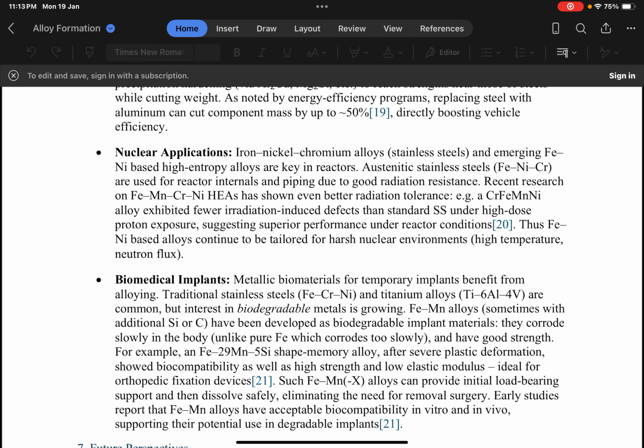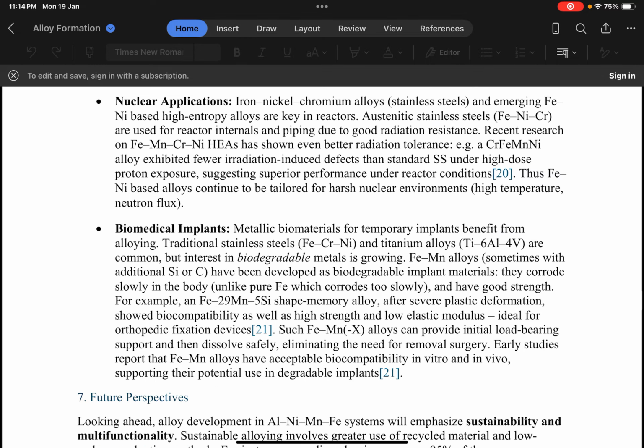Iron-nickel-chromium alloys, stainless steel, and emerging iron-nickel-based high entropy alloys are key in reactors. Austenitic stainless steel, iron-nickel-chromium, is used for reactor internals and piping due to good radiation resistance. Recent research on iron-manganese-chromium-nickel high entropy alloys has shown even better radiation tolerance. For example, a chromium-iron-manganese-nickel alloy exhibited fewer irradiation-induced defects than standard stainless steel under high-dose proton exposure, suggesting superior performance under reactor conditions. Thus, iron-nickel-based alloys continue to be tailored for harsh nuclear environments and high-temperature neutron flux.